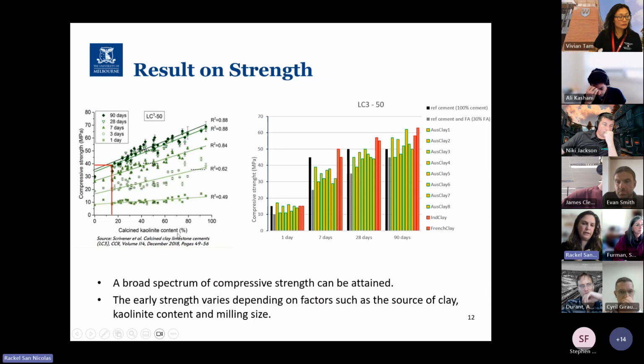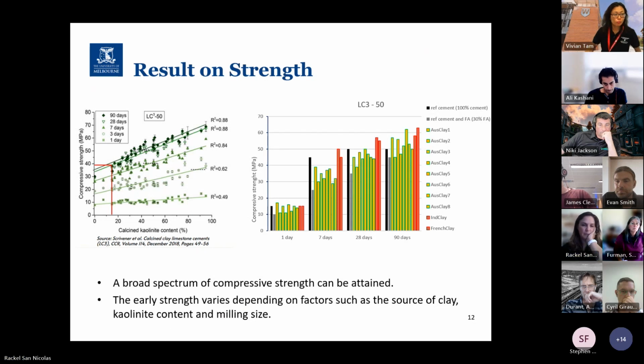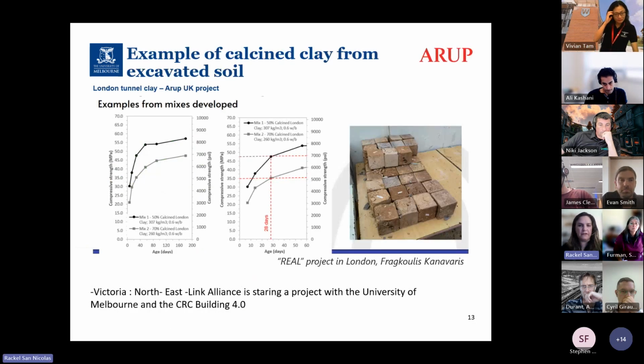And the richer in kaolinite your clay is, the better performance it has. However, you can see that even when you've got a very low amount of kaolinite in your system, you still can reach 40 MPa. That's really the point I want to make. Depending on the application that you are targeting, you can actually reach proper properties. Here are some results that we have on Australian clay. What is interesting to look at is we don't really have a delay at early strengths, depending on the clay, especially when comparing to a reference or to a fly ash mix with 30% fly ash. We are within the range, and you can see that we can reach very nice compressive strengths later on as well. So we've got a broad spectrum of compressive strengths.